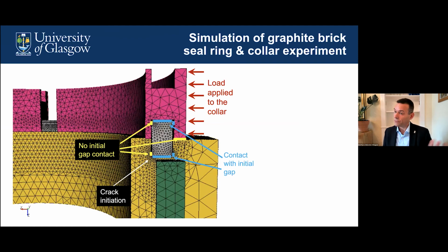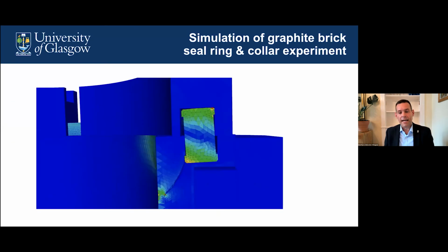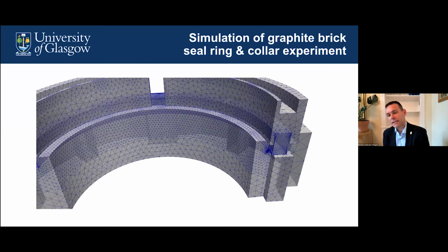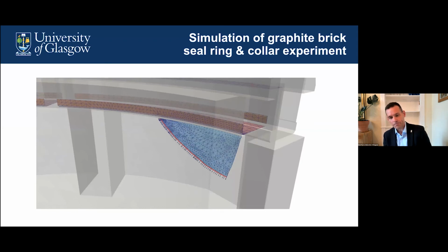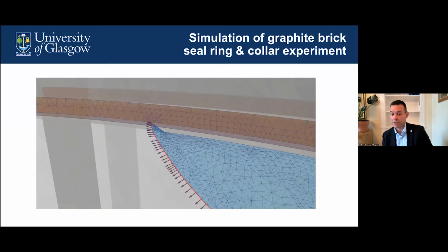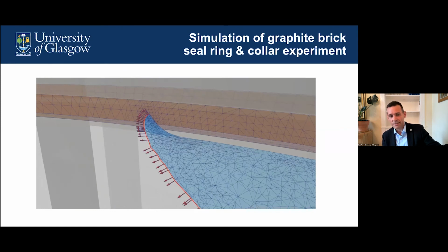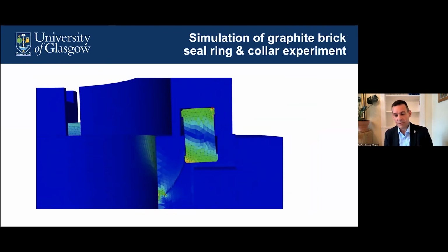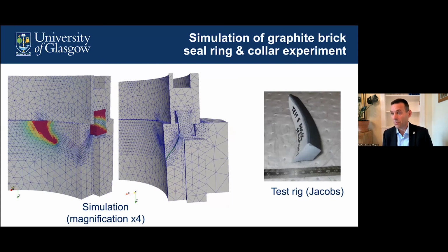So the real problem we're trying to solve is an experimental setup to predict what's happened in the reactor, because in some of the reactors you have bricks that have a seal between the bricks, and therefore you've got this complex contact as well as crack propagation. So we've got a situation where we've got some contact with initial gap and some contact with no initial gap. And this final animation, I'll stop after this, just shows you our predictions of the crack propagating. The red surfaces are the contact surfaces, and you can see the analysis is struggling a little bit, but it makes it through and goes through that contact surface. And as a result of that, you end up with this fragment that we're predicting.